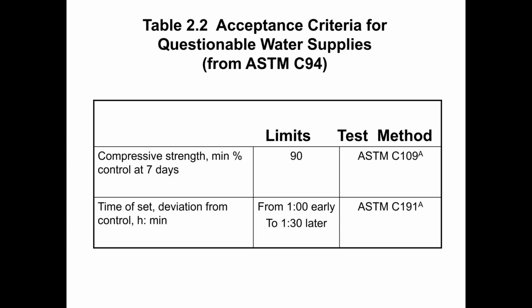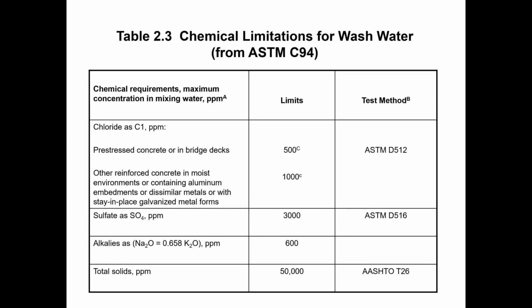All right, sometimes we use wash water in the batching process. This is especially true for ready-mix concrete. And so if wash water is going to be used as a component of the concrete, then we need to do some testing on the wash water to make sure that it meets certain requirements before we can clear the use of the wash water. So shown in table 2.3 are the primary requirements with regard to chlorides, sulfate, alkalis, and total solids. So as long as our wash water meets these limitation requirements according to these test methods, then we can use a portion of the wash water as mixing water in our concrete.